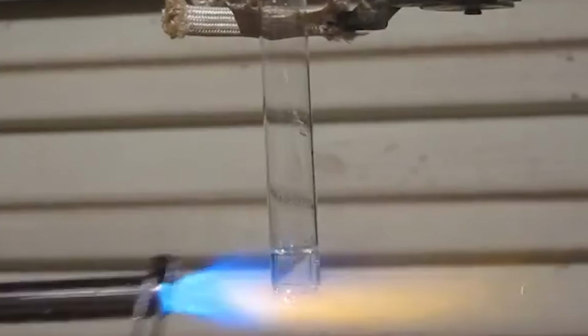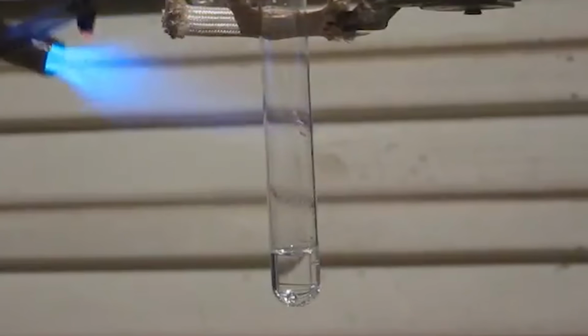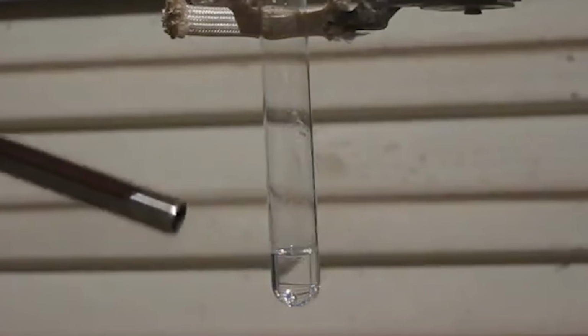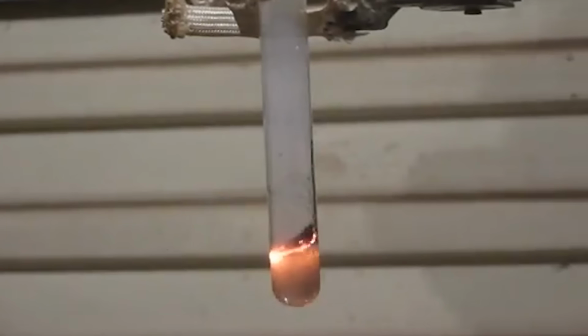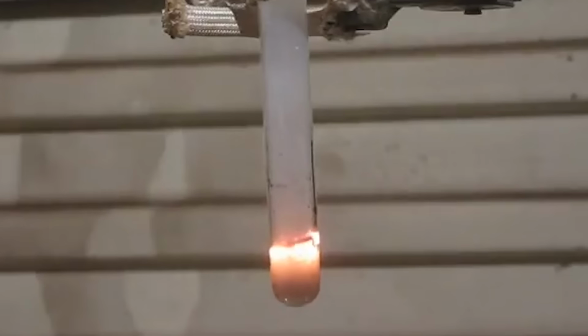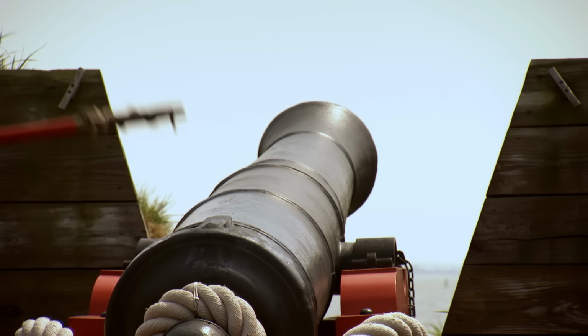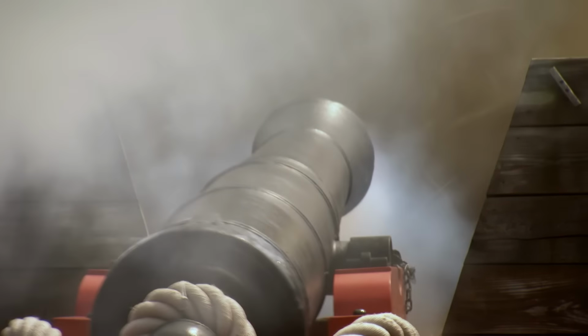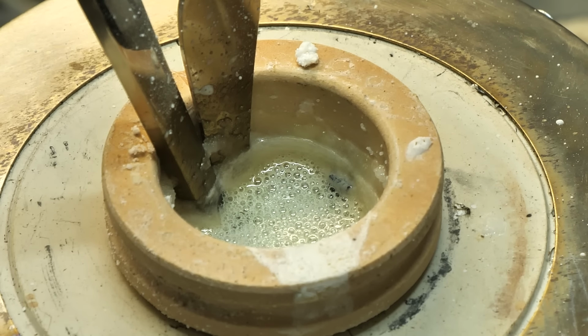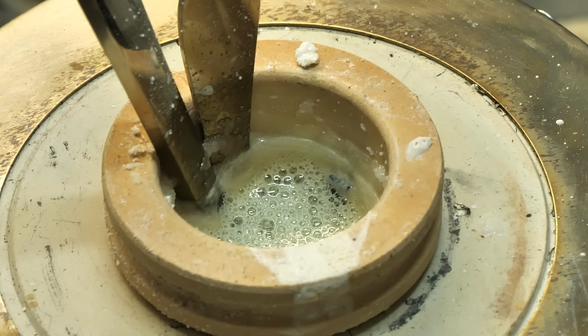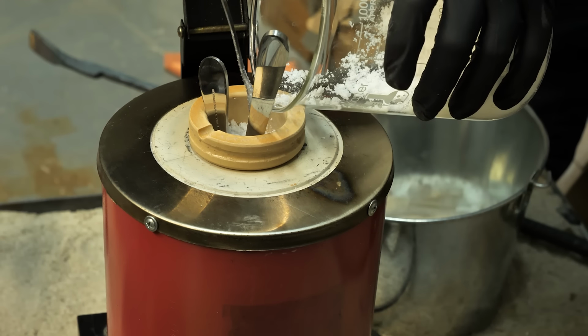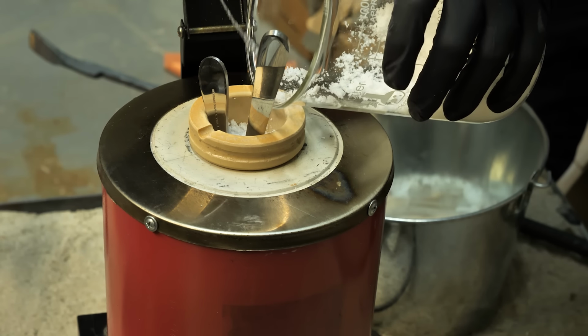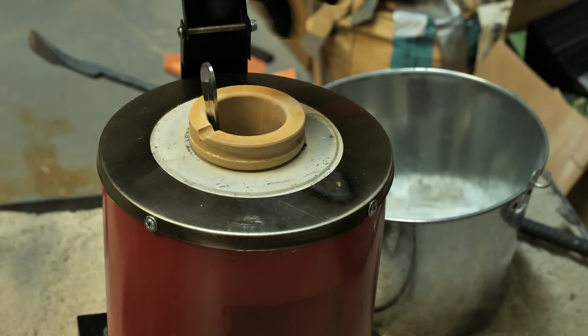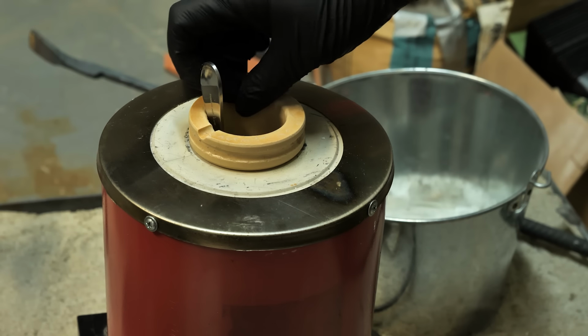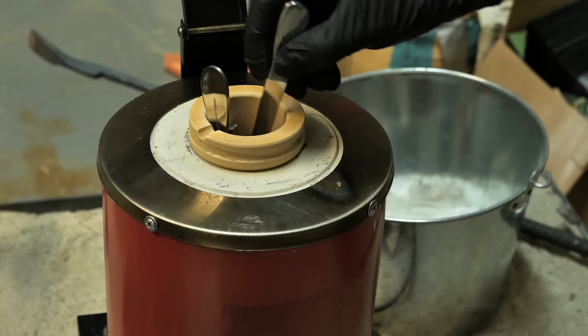Speaking of intense oxidation, one thing we realized as we were preparing for this experiment is that our normal graphite crucible probably would have turned into a bomb, or at least a very big fire if we'd tried this in it. Black powder is, after all, a nitrate salt and a carbon source, so a molten bath of nitrate probably would not do nice things to graphite. To remedy this, we picked up a nice alumina crucible which won't react. The bath needs to get up to about 650 degrees, which is much colder than the usual case hardening temperature.